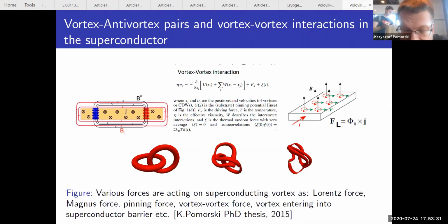When this normal phase flows, there are unpaired electrons in the core of the vortex, and these electrons feel electrical resistance. So there's a certain level of dissipation. The flow of vortices can be spotted very well by the current-voltage characteristics, and there's some level of dissipation, which is already tricky in quantum mechanical description.